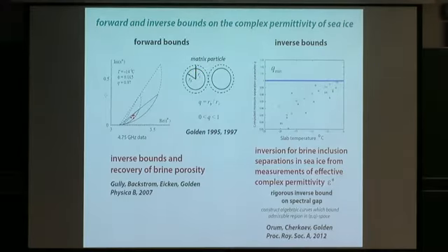That's something new here. And so there's a parameter Q. These are like circles. So that's the brine, R sub B, the brine, and that's the ice. There's like little spherical shells of ice that protect the little brine inclusions from each other. And when Q goes to 1, that means they start to touch. And anyway, so we got these beautiful tight bounds. Actually we were the first, I think, to derive complex bounds for matrix particle composites.